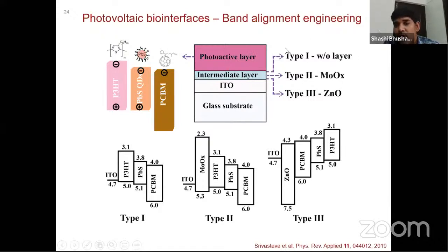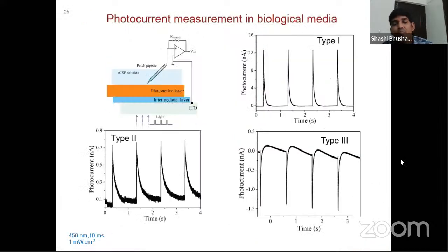So what we did, we didn't put any intermediate layer. It was with ITO and photoactive layer. So this is the band alignment corresponding to that. Then we put the molybdenum oxide in between the ITO and photoactive layer, and the band alignment gives us hole movement towards the ITO and electron movement towards the biological interface. However, when we put zinc oxide, the band alignment tells us that towards the ITO, the electron will come here, and we are going to put the biological interface at this place, so the holes will be there.